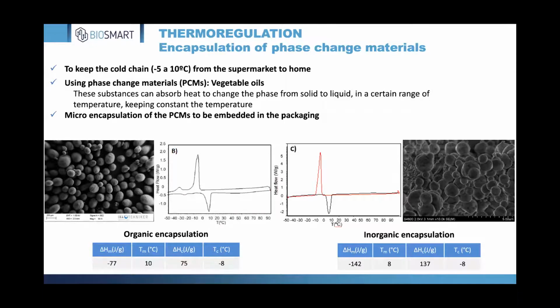Another way to achieve functionality is to encapsulate the bio-based packaging with phase change material. This allows the thermoregulation of the packaging, increasing the time where you can keep a temperature between -5 to 10 degrees. We have used vegetable oils to achieve this, and these vegetable oils allows to keep constant the temperature when is transforming the phase. And it has been achieved by organic encapsulation or inorganic encapsulation. Being the inorganic encapsulation have a higher capacity of keeping the temperature constant.